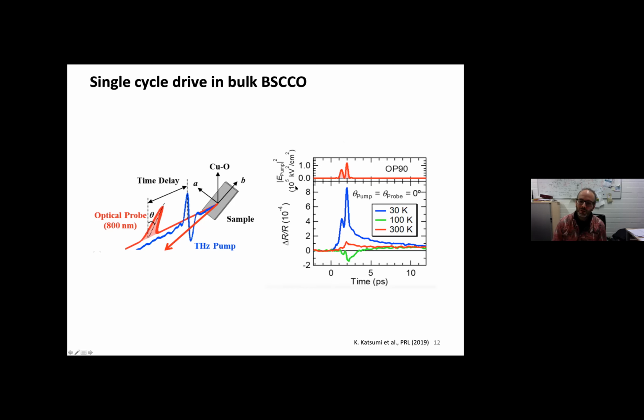But now jumping really to first experiments. So if we perform now, for example, an attempt to quench the superconducting condensate, for example, on a BSCCO sample. So we come with a very short high field terahertz pulse, and then we probe this optical response and we try to look for transient oscillations of the system. Then we don't find them in, for example, optimally doped BSCCO of these materials. All oscillations that we find here are only the 2 omega oscillations from the driving field whilst the pump is there. But there is no oscillation that can be found here on the transient response.